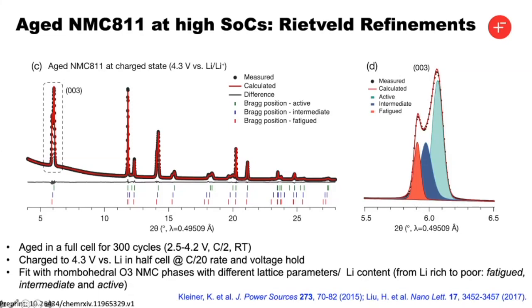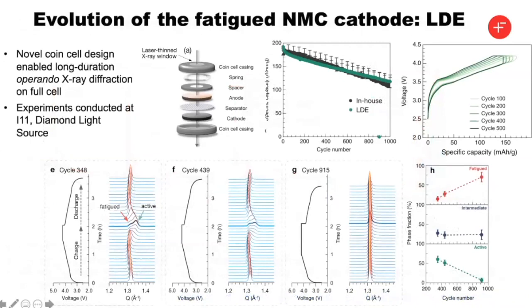And I just want to point out that Gasteiger's group and others have also seen similar sorts of phenomena in NCA materials on multiple cycles. So what we've done then is to move to the light source and use laser-thinned coin cells so that we can use a standard coin cell to study these long cycle experiments without any worry about moisture and contamination.